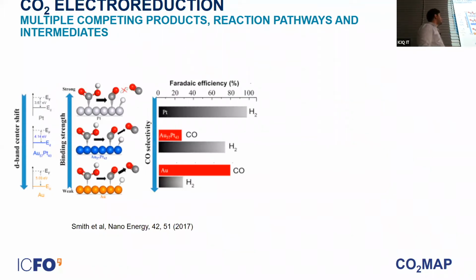One of the most well-known strategies now is to control the way metals interact with the reactants, how metals interact with CO2 or with the subsequent reaction intermediates. In this example here, you can see how by alloying platinum and gold, for example, you could change the electronic properties of the alloy, and in doing so, change the binding energy of the metal to the molecules that you want to transform. In this case, the binding energy to CO.